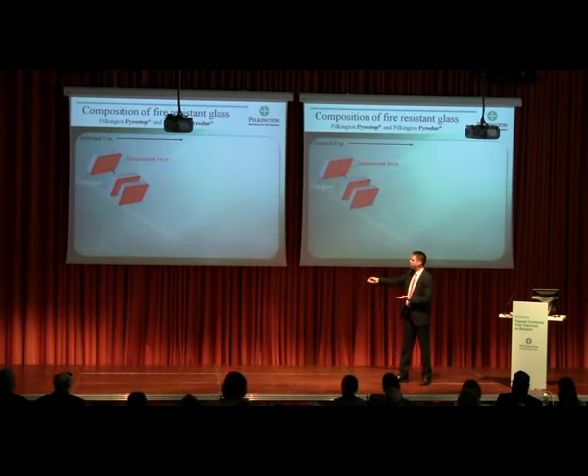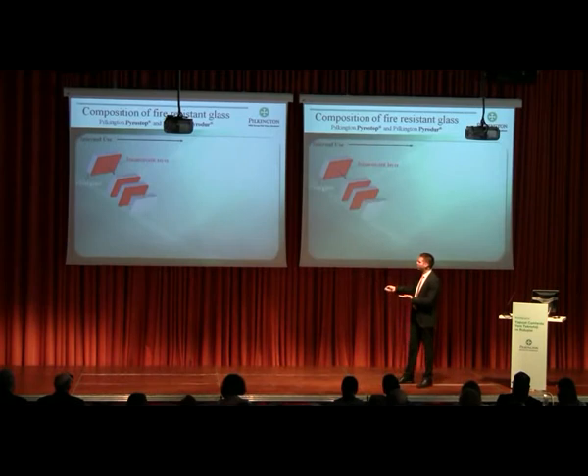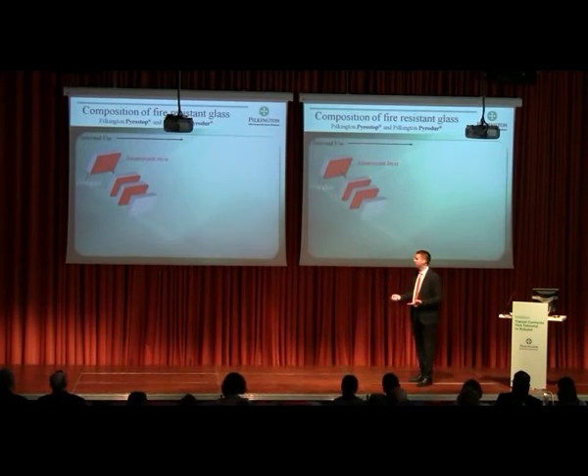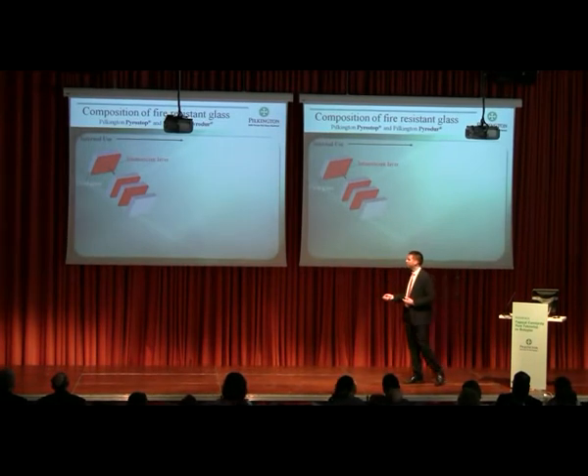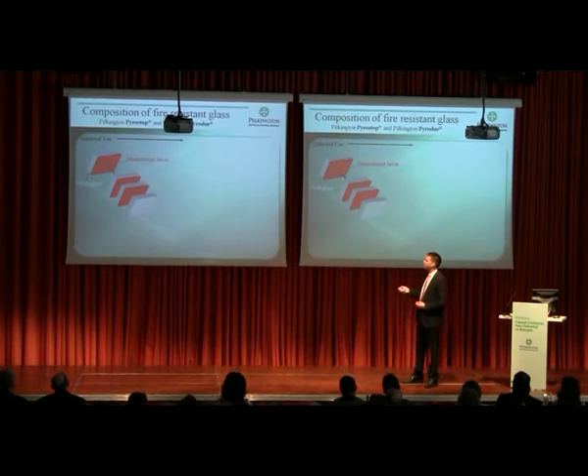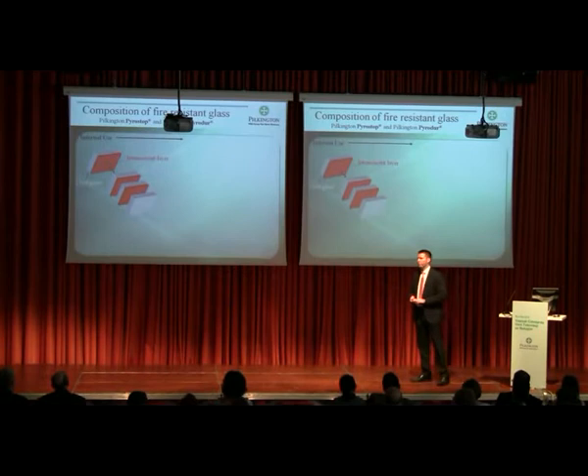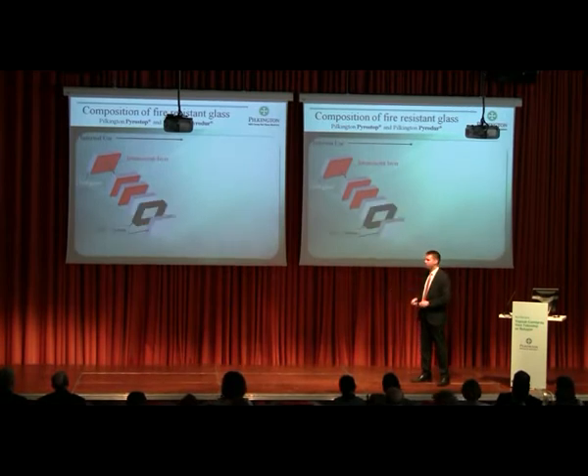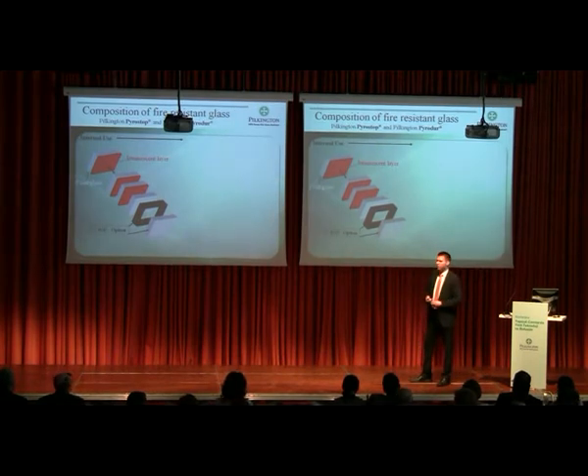So what we do is, we take several panes of float glass with several interlayers in between those float sheets. And we put together a kind of sandwich. So several float glasses with several interlayers foaming up in case of fire. So this is the basic construction of a Pyrostop and a Pyrodur glass. What else is possible? Of course, you can build up double glass units for additional sound control requirements or solar control requirements, whatever. So all you know from the non-fire protection glasses, more or less also possible with fire protection glass.